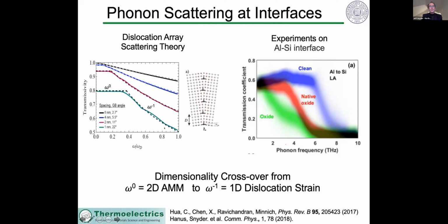And that leads to a frequency to the -1 behavior of the transmissivity, which we think leads to a dimensionality crossover in the behavior of the scattering and transmissivity of phonons at interfaces. Some hint that this appears experimentally is in Austin Minnich's work, looking at the transmission coefficient as a function of frequency in a variety of different materials.